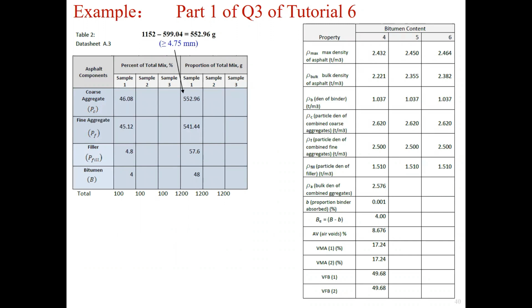So the weight of coarse aggregate is 552.96 grams. If we divide this value by the total weight of 1,200 grams, we get the PC value of 46.08 in percentage. Similarly, we could work out the PF and PFill.